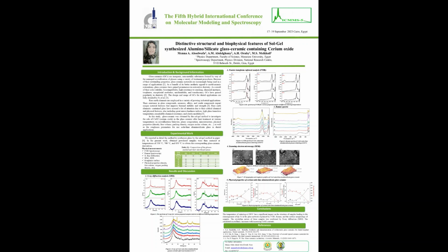From FTIR shown in Figure 3, the band at 935 conjugated with the band at 1038 when temperature increased during treatment because of rearrangement of QN units, especially in Q2 and Q3. The band at 443 increased in intensity and width with sintering due to the modifier. Figure 4 shows FTIR spectra of CeO2 soda-lime aluminosilicate glasses sintered at 850.